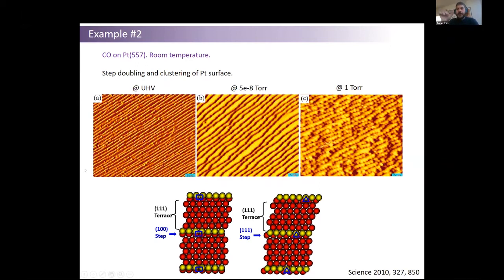So for every 6 atoms on a terrace, you are going to have a monatomic step, a small step. So that gives you 10 degrees miscut. And this is how it looks in ultra-high vacuum conditions under STM imaging. So it's a large-scale STM image, actually, but this is satisfactory for the purpose of this work. And you see that once carbon monoxide is dosed, already at low pressures, the width of the terraces is now double, and also the height of the steps are doubled.